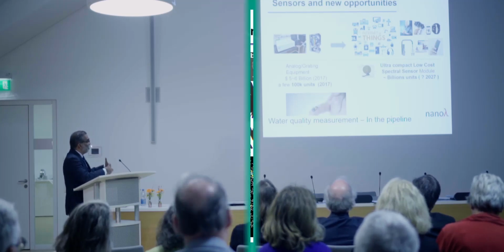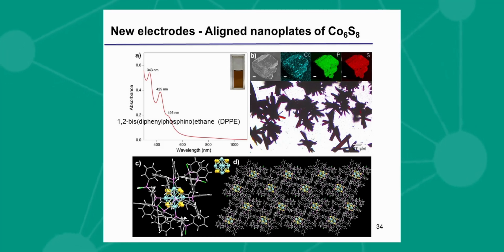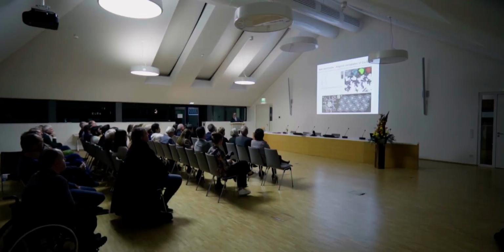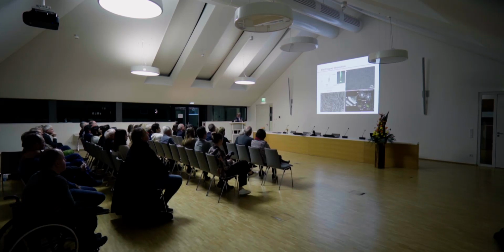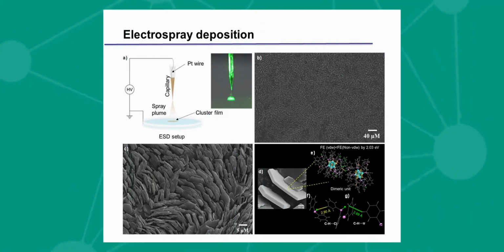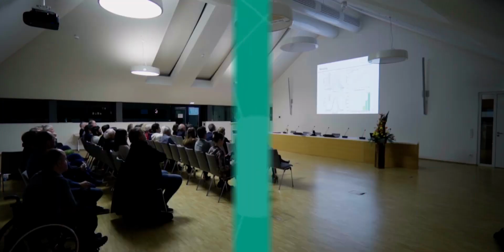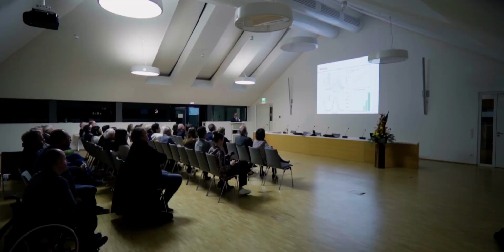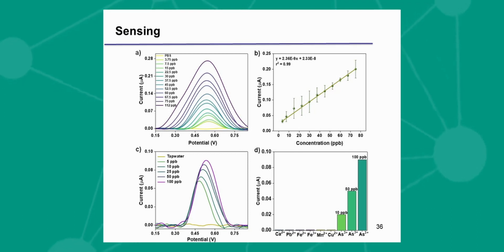And with that, with the analytics, with the data over the cloud, it is possible to measure a Google map of water quality. And we think that it is possible to be done with atomically precise clusters. So here is a cluster in the laboratory that we make, similar to what Stephanie makes here. These clusters can be electrosprayed by a technique called soft ionization methodology onto water surfaces, creating micron scale platelets. And they are extremely sensitive. As you see, they are sensitive to arsenic. And with real tap water, without any purification, put a drop of it, and you can measure arsenic down to 3.7 ppb. And so selective that no other ion gets detected.